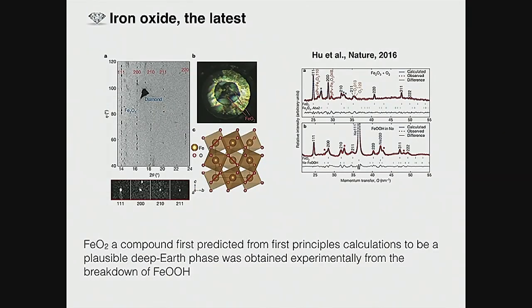There's another oxide being proposed. You will see that this is particularly interesting to me. This is an iron peroxide. I don't think you heard about this compound before. This was synthesized around 100 GPa and might have important consequences for deep Earth and deep planetary interiors behavior, especially of these light elements, including oxygen, hydrogen. And again, the diffraction patterns, you see both the image and the pattern, they probably don't look like what you have exercised on.